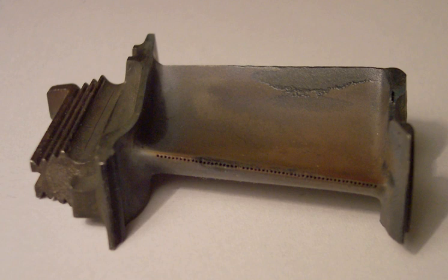When temperature exceeds 1000 degrees Celsius, the rafting effect is prevalent, where cubic particles transform into flat shapes under tensile stress. The rafts would also form perpendicular to the tensile axis, since gamma phase was transported out of the vertical channels and into the horizontal ones. After conducting uniaxial creep deformation of oriented CMSX4 single crystal superalloy at 1105 degrees Celsius and 100 MPa, Reed et al. established that rafting is beneficial to creep life since it delays evolution of creep strain. In addition, rafting would occur quickly and suppress the accumulation of creep strain until a critical strain is reached.